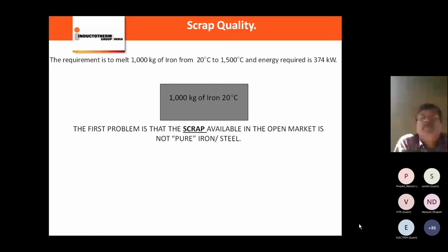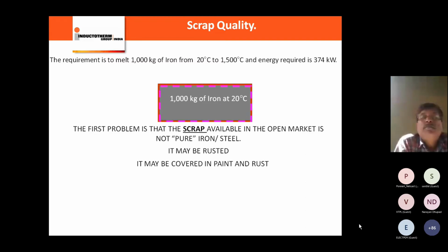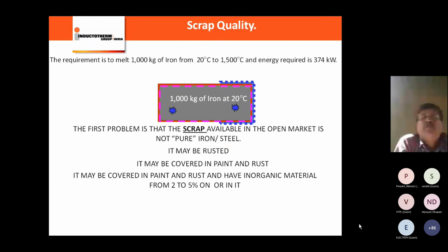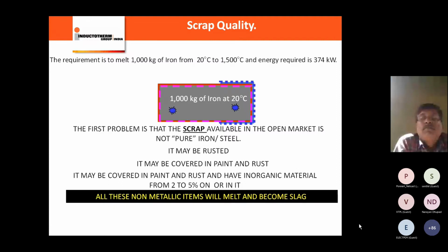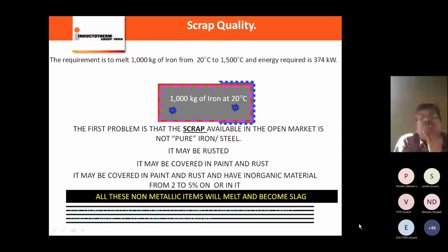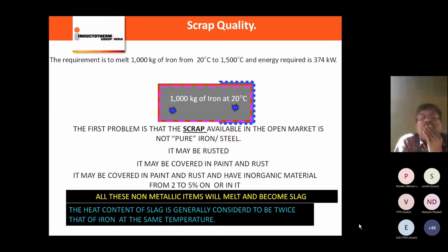So the first problem is that the scrap available in the open market is not pure iron or steel. It may be rusted. It may be covered in paint, rust, and have inorganic materials from 2 to 5% on it. Sometimes borings contain a lot of oil and inorganic, non-metallic items that definitely contribute to energy consumption. All these non-metallic items will melt and become slag. The heat content of slag is generally considered to be twice that of iron at the same temperature.